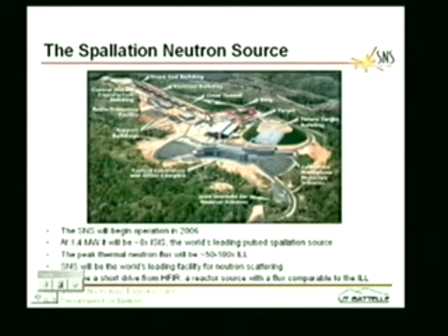Having accelerated H- ions up to 1 billion volts, we strip the electrons off and collect them in an accumulator ring, which doesn't accelerate. What it's doing is compressing the pulses. We get a millisecond pulse out of our LINAC, and then we wrap it 1,000 times around the compressor ring and spit it out in a single turn. So the pulse width goes down by a factor of 1,000, the pulse intensity goes up by a factor of 1,000. So we wind up with a microsecond pulse of protons, which we deliver 60 times a second to a liquid mercury target.